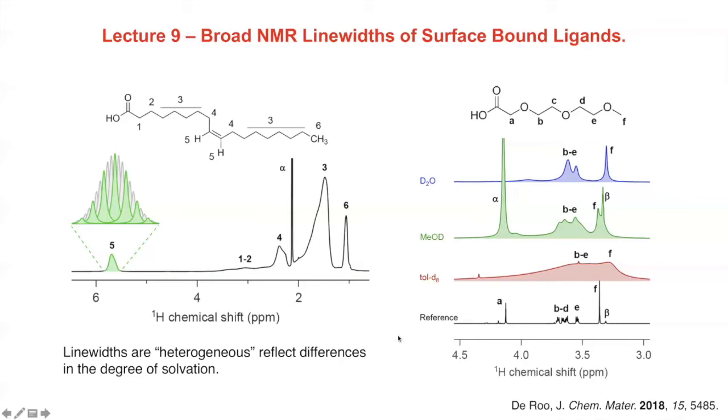So the breadth somehow reflects changes in the solvation. And nonetheless, it allows you to distinguish, say, this sharp peak, which is from something free in solution, not bound to a particle, from these broad resonances that are coordinated. Another one here. This is a solvent impurity, and very sharp small molecule versus broad for bound to the surface.